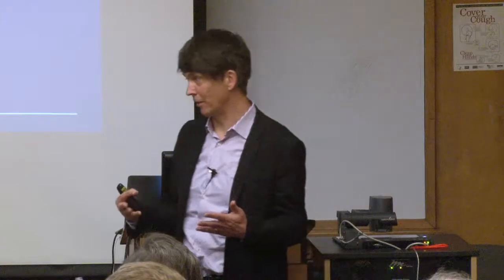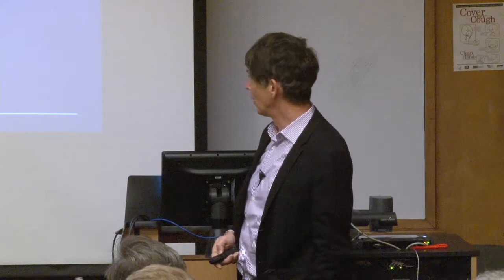And there are people who've claimed that the yield strength of lithium in confinement is 200 megapascal. And I go like, well, I've never seen that kind of confinement effect, right? Going from 0.7 to 200. But this is one of these real puzzles in the battery field today. If we don't solve it, we will not use lithium metal, because we have to be able to deal with the mechanics issue of lithium.